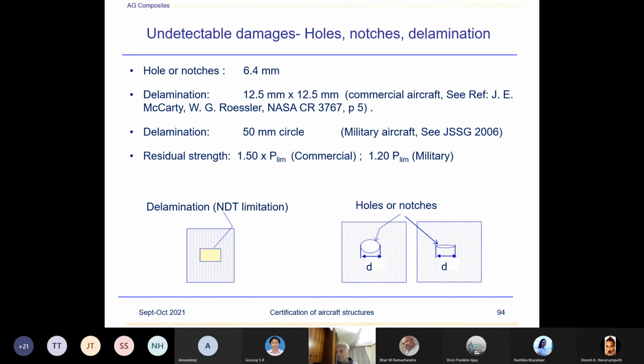So residual strength degrades quite rapidly when you have a 50 millimeter circle compared to half inch by half inch damage. However, the residual strength requirements are similar to the previous one: 1.5 times limit, that's the ultimate load, for commercial, while 1.2 times the limit for military aircraft. I've just shown schematically the delamination and NDT limitation, holes and notches.